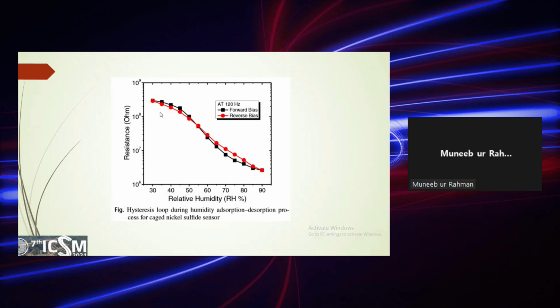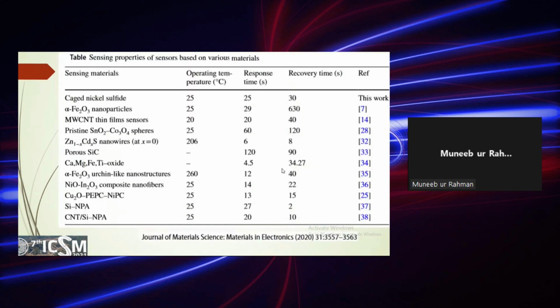As we increase the humidity, a water layer is added, and that is why the resistance of the device decreases. Then we gradually decreased the humidity in the reverse order to check the hysteresis of the device, which we see here is very low. For a good sensor, the hysteresis loop should be as narrow as possible. So we then compared our results with already published work found in the literature.